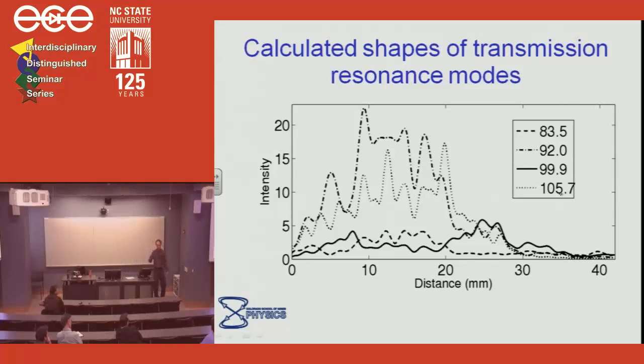Here is, so first of all, I should say, what do you expect generically? If I have a random arrangement of quartz and Teflon layers, the generic behavior for almost all frequencies is if you put a plane wave in, it decays exponentially. For almost all frequencies. That's the generic behavior. Okay? This is non-generic behavior. These are those very special frequencies where you don't get exponential decay. In fact, you get this tremendous enhancement. This particular mode is enhanced by more than a factor of 20. Okay? And this enhancement is caused by just the multiple scattering inside this randomly oriented one-dimensional system. So this is the signature of Anderson localization. So these are localized modes inside the random system.